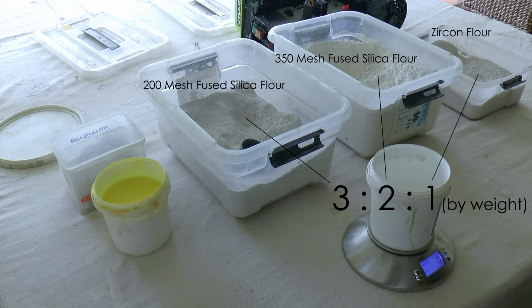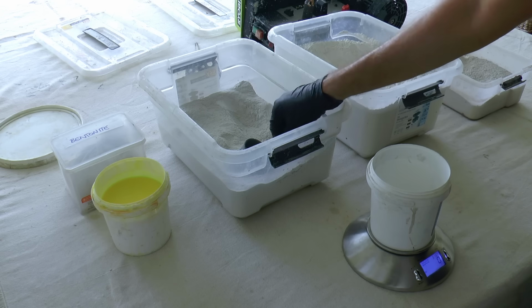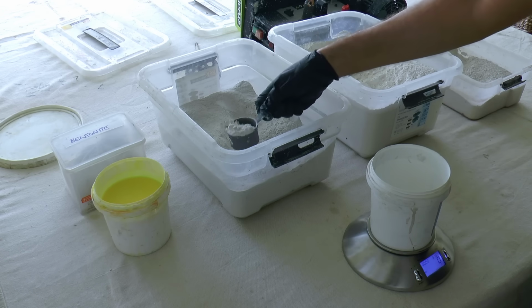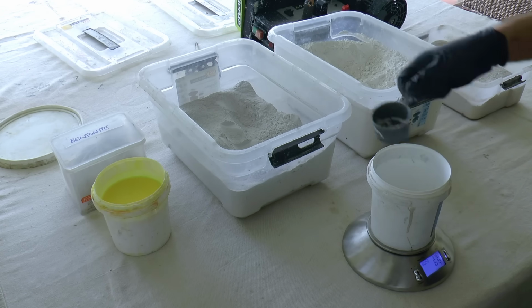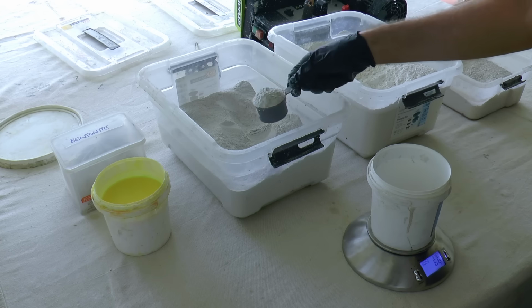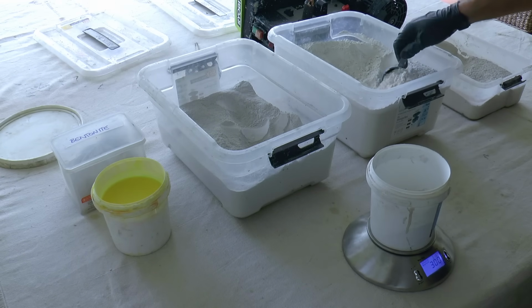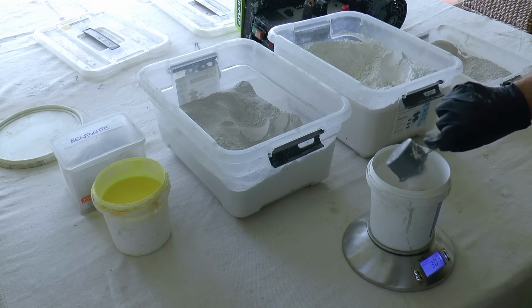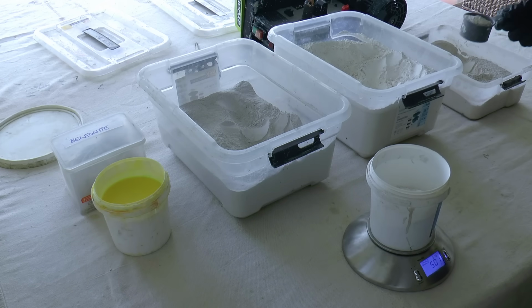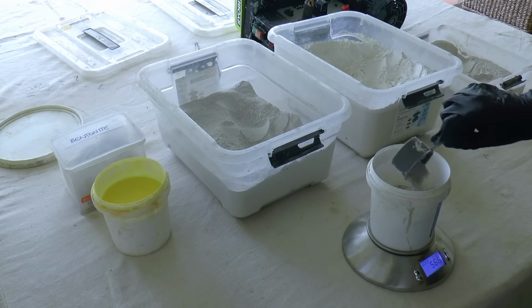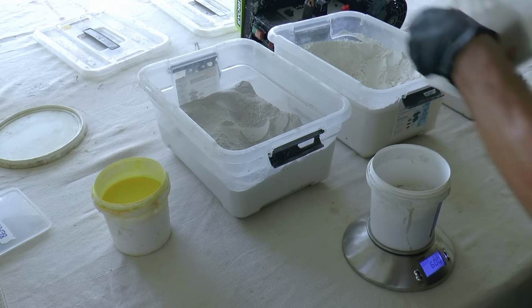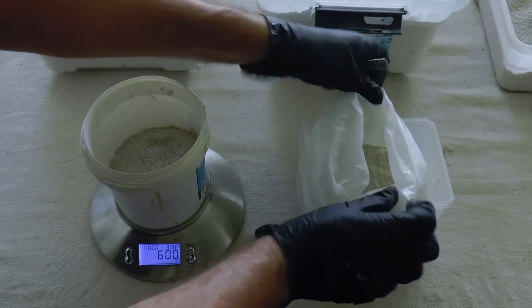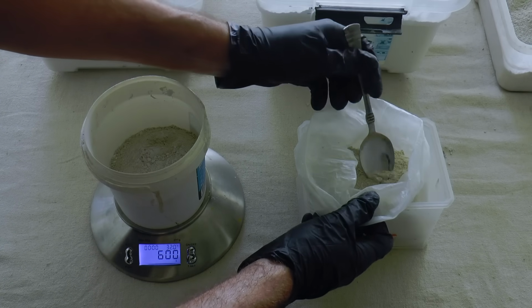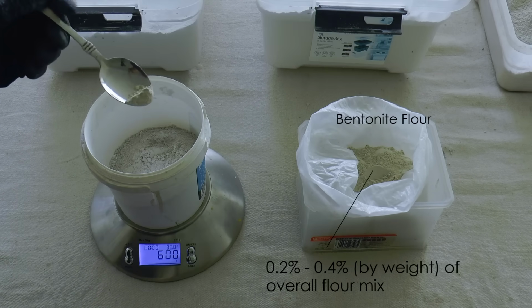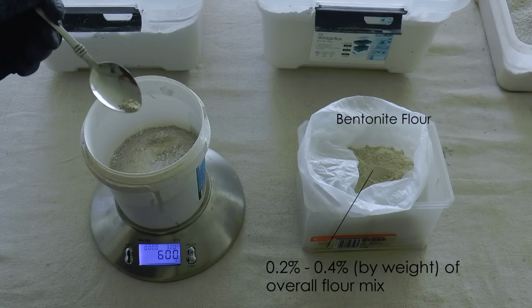I've found that blending 2 fused silica flours with zircon flour produces a versatile mix. It results in a slurry that works well for the entire temperature range of the metals that I work with, although 200 mesh silica flour on its own is perfectly fine for most use cases. Now the flour has a tendency to settle quite quickly once mixed with the colloidal silica binder, so a suspension agent is required to slow this down. In this case, bentonite flour serves the role well.